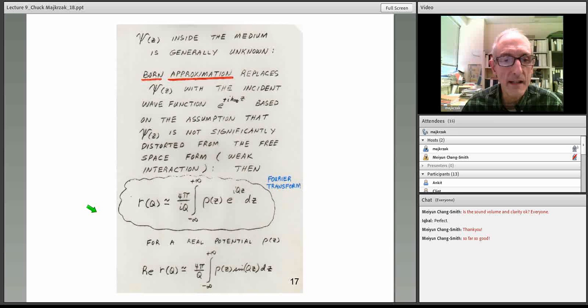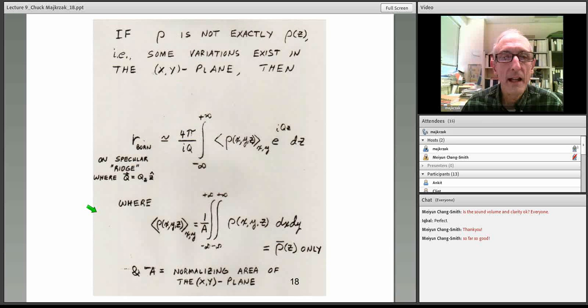Well, that's nice, and I just point out here again that even if the surface is not perfectly homogeneous in plane, if it's sufficiently small variation compared to the variation as a function of depth, then what we really measure is the average scattering length density in plane. And we'll say more about this later. And we can still get a legitimate specular reflection relationship that gives us the scattering length density profile for this in-plane averaged quantity.